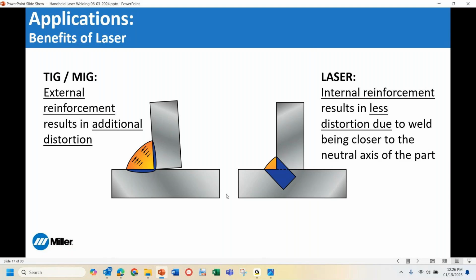With the laser, we have a lot less external reinforcement, and we're relying more on the internal reinforcement. And that puts the weld metal, or that molten solidification area, closer to the neutral axis of the part. And also, because we have less heat soaking into the surrounding material, because the process is much faster, we are limiting the amount of heat in the component, all of which contribute to the minimal distortion with the laser process.